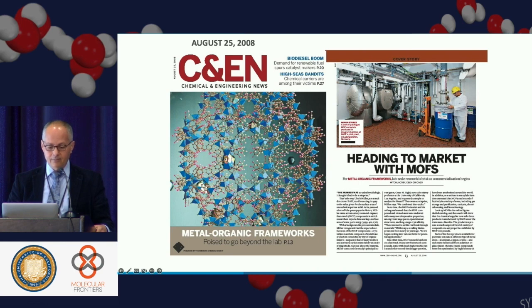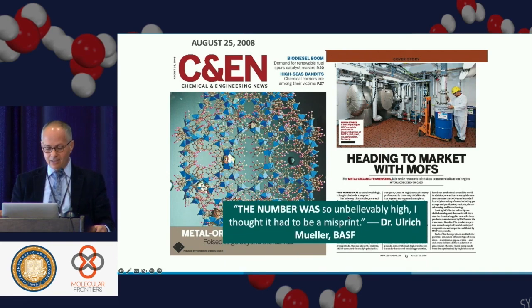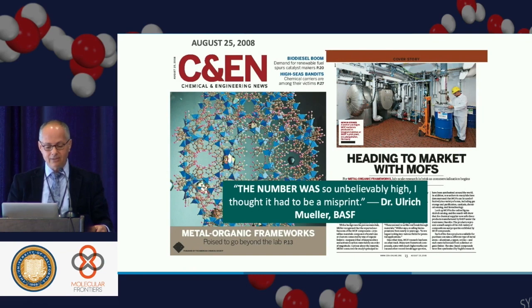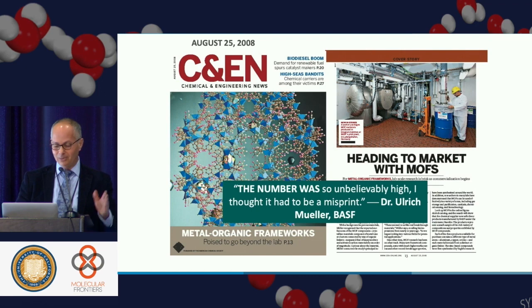Much later, there was a nice article written on C&EN about commercialization of MOFs, and they had interviewed one of my very early collaborators at BASF, and in this article, I learned for the first time that when we reported the surface area of MOF-5, he thought the number was so unbelievably high that it had to be a misprint. And that started my collaboration with BASF. They didn't really believe that that surface area is real. They thought that we missed a decimal or whatever. And this is a picture of them scaling, and I'll show another one, scaling the MOFs at multi-ton quantities.